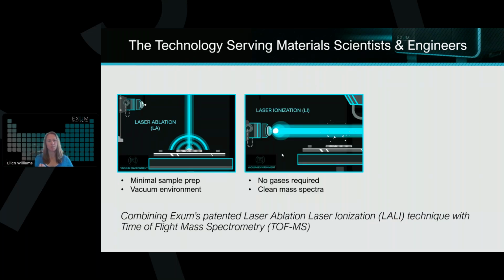Once we have that ablated plume of particles, we then use a secondary laser to create ions. Every mass spec technique needs ions. The way that we're doing it here with laser ionization, we're essentially just stripping off an electron from the neutral particles, meaning we're not creating ions from a plasma like the ICP techniques. That P stands for plasma. We're not using any sort of argon gases or other gases that can create interferences. The result is that once we get our ions, it's very easy for our software to act as the analytical chemist and isotopically verify all of the elements that you have in your material.